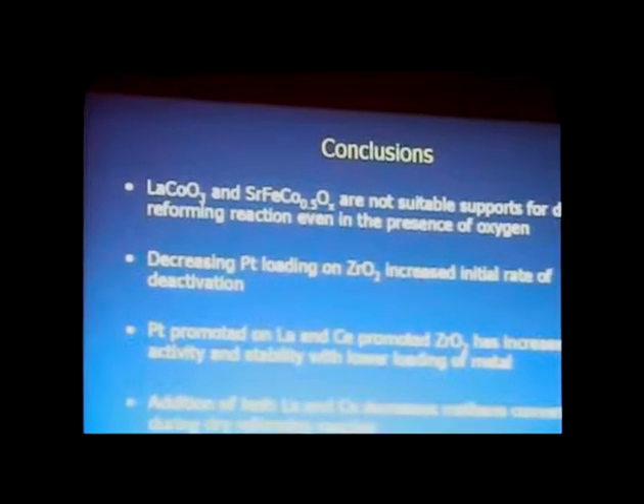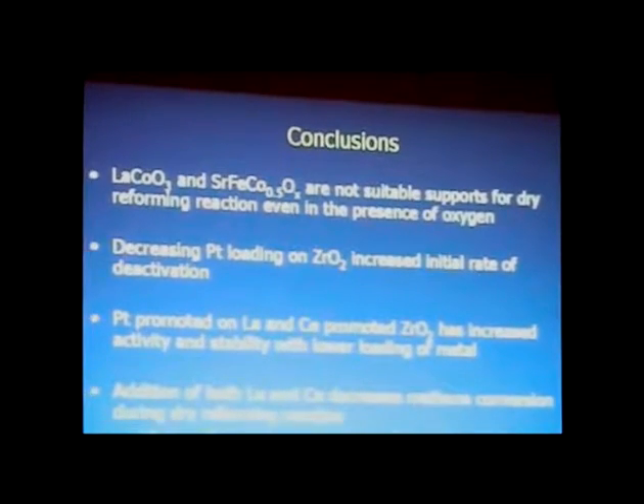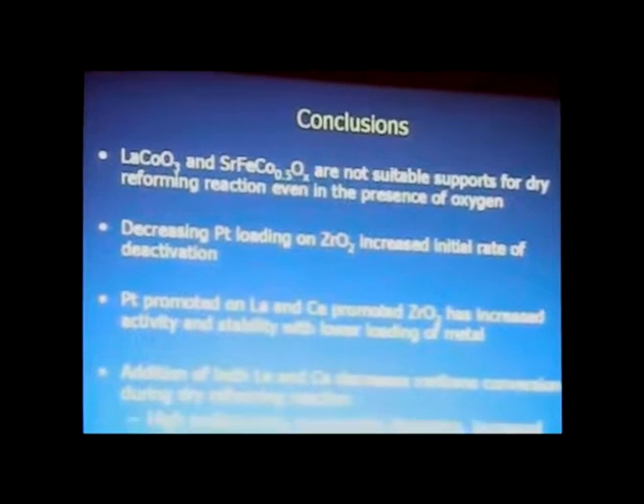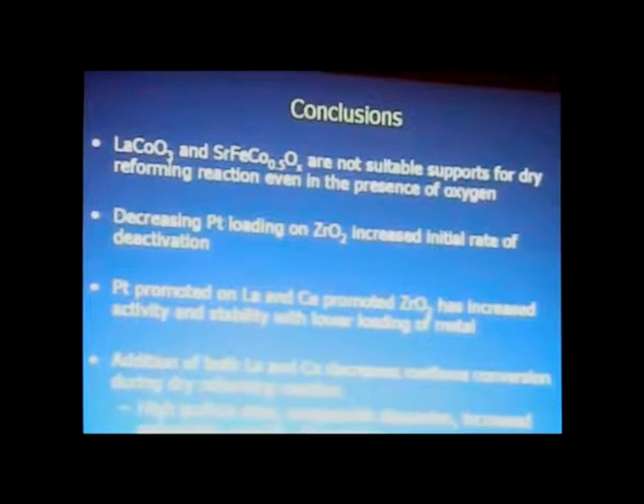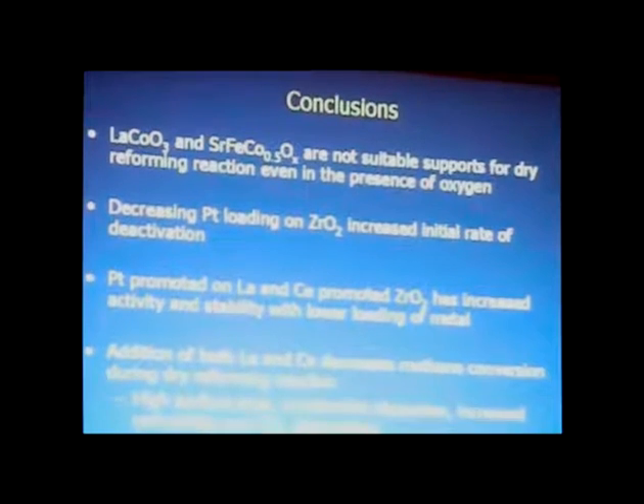So in conclusion, we showed that LaCoO3 and SrFeCo0.5Ox are not suitable supports for the dry reforming reaction, although this material with nickel in it has been shown to be very active for these reactions. Decreasing the amount of platinum loading on zirconia increased the initial rate of deactivation, which we believe is due to sintering, but then after that, the rate of deactivation was very similar to the higher level material.